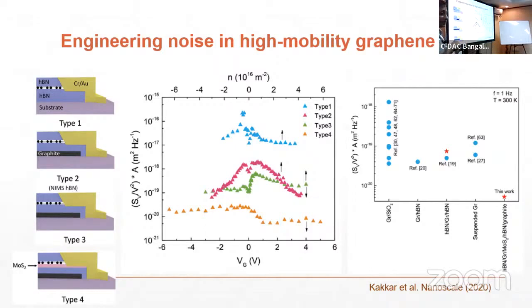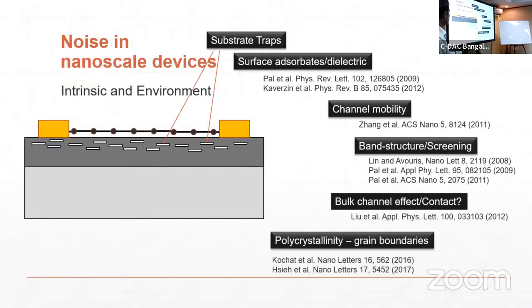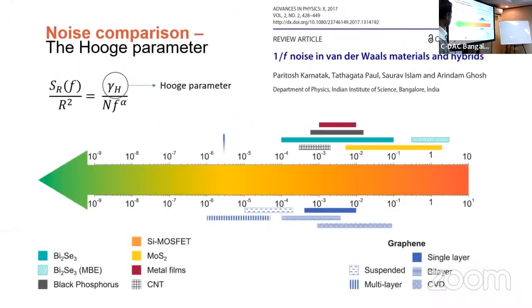But it turns out that even if you put boron nitride, which is expected to be a single crystal, it has large levels of charge because of the defects in the boron nitride. And those charges actually give noise. So whatever noise is left is given by them. So we tried to screen that out by using another semiconductor, which screens the charges in the dielectric environment. And that led to an extremely clean two-dimensional system with very low noise in graphene, the lowest noise that people have observed. So that's the direction we have taken in 2D materials.